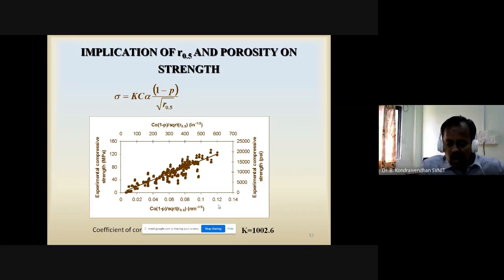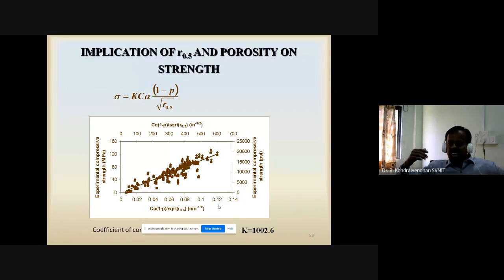Generally, in the literature, mostly they have said compressive strength is governed by the porosity only. Actually, that is not correct. The compressive strength is not only governed by porosity, it is also governed by pore sizes. Only very few people have done this kind of work. In the very beginning, Atal did such work, incorporating the pore sizes along with the porosity. Later on, Kumar and Bhagath also gave such a relationship: sigma equals Kc into 1 minus P divided by R.5. For cement paste, we slightly modified that, because in cement paste we have to consider the degree of hydration also. That's how we got sigma equals Kc alpha into 1 minus P divided by R.5.